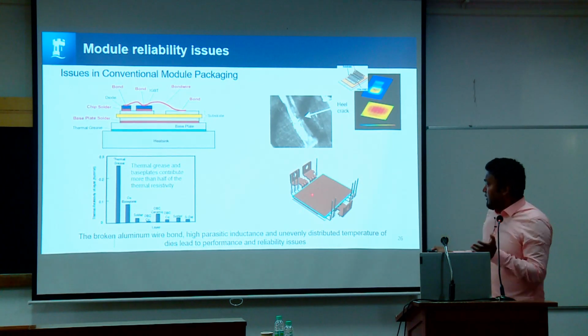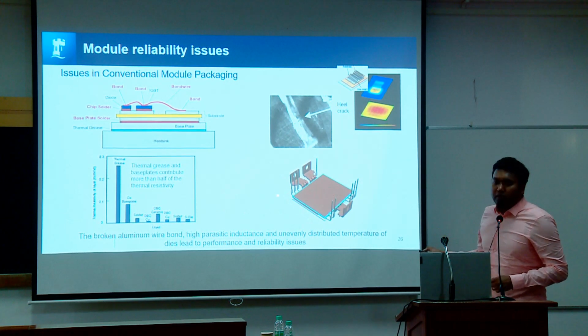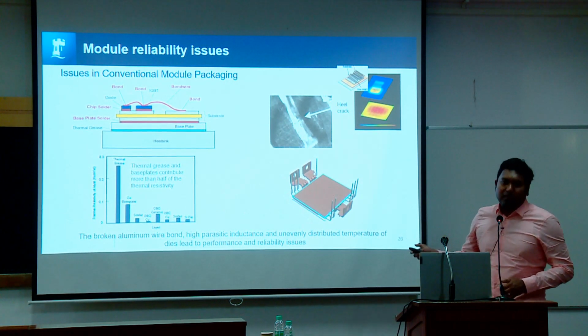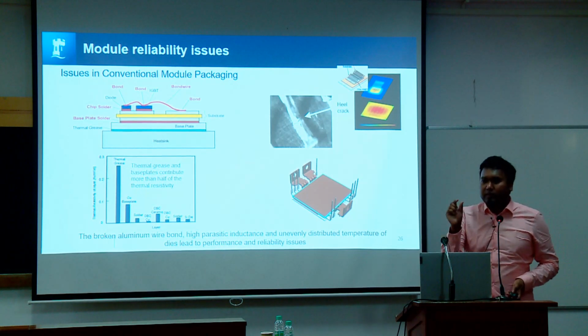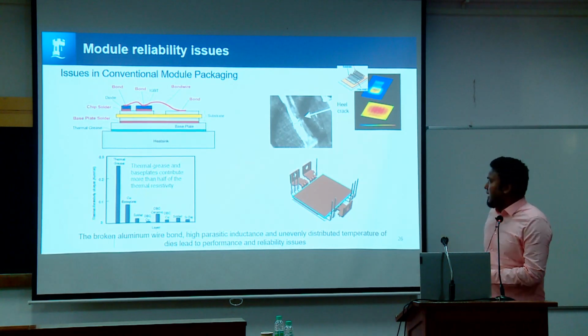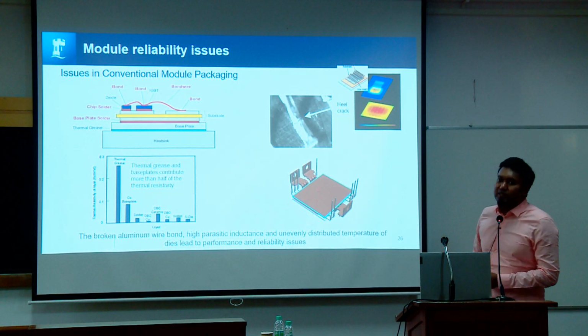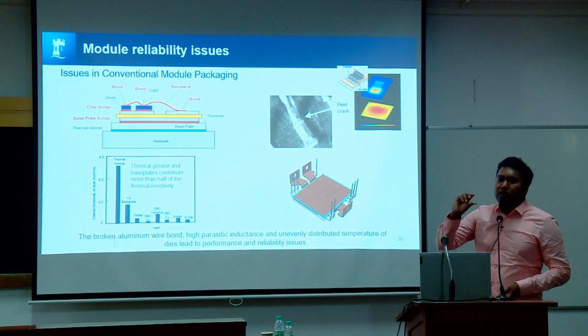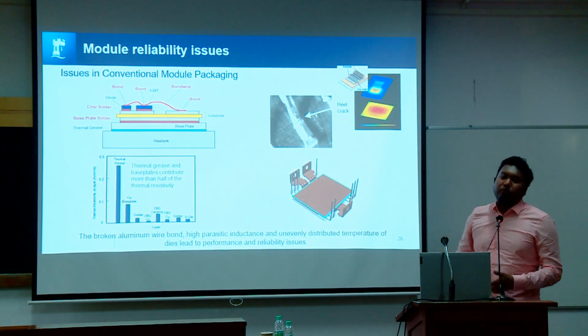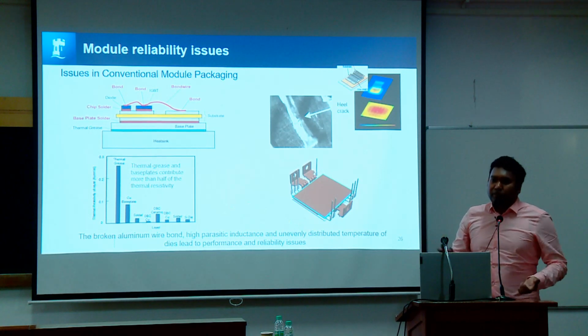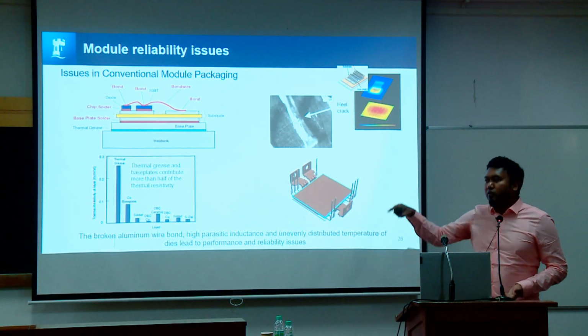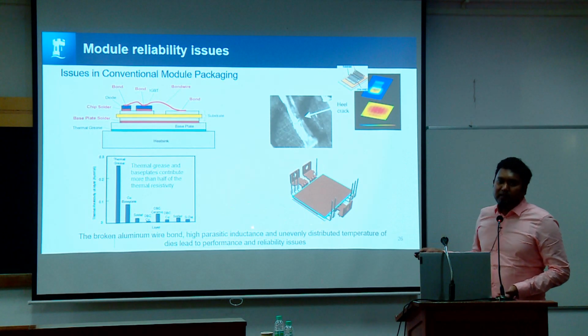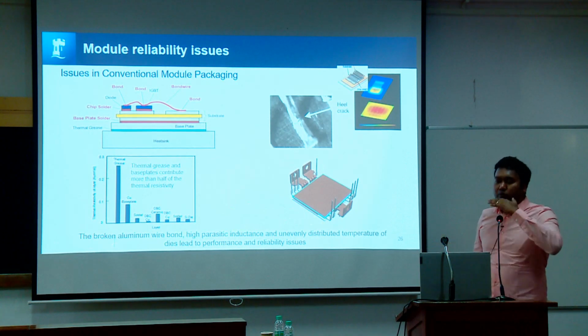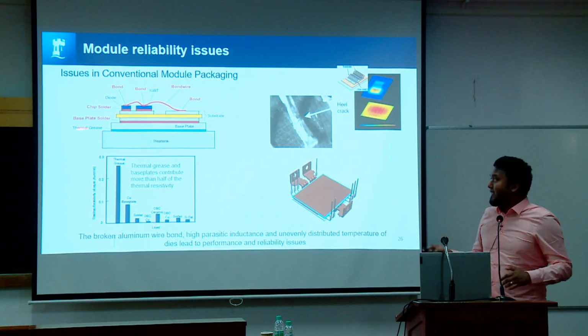And we have seen also, when I was working at Dynex, we built a double-sided cooled module. We replaced the wire bonds with copper moly, just small little bumps of copper moly, and put 2 DBCs, sandwiching the devices between the 2 DBCs. Even after doing that, when we run the power cycling test, when we heat up the devices and cool down, heat up, cool down, we'll see that the device starts to fail, and starts to fail where, for example, the copper moly is connected with the device. So it's an inherent problem.